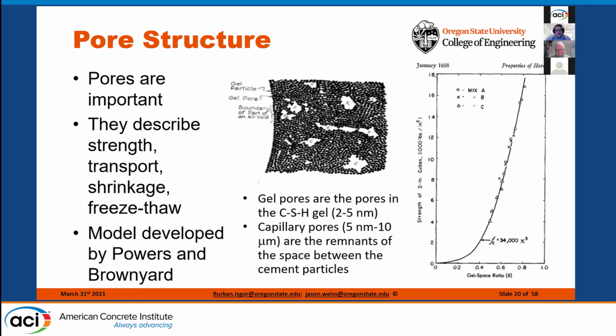And what I want to suggest here is that pores are really the critical factor that's inside of the concrete. The pores are going to describe the strength, and the strength is really primarily driven by the capillary porosity, and that's these bigger pores from this picture from Powers almost 70 or 80 years ago. The capillary pores are going to be between about 5 nanometers and 10 microns. They're the leftover space between the cement particles inside of the system. The pores are going to dictate transport, and this is going to be primarily, again, the capillary porosity. They're going to dictate the shrinkage of the overall system.